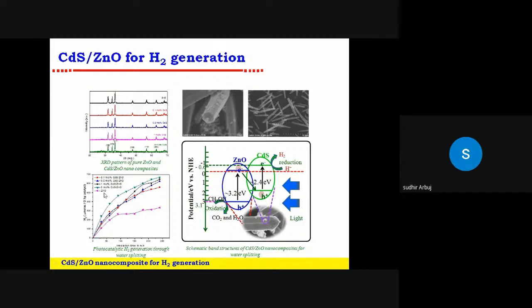So we observed that the 5 mole % CdS-loaded zinc oxide gives the highest hydrogen generation over zinc oxide. Pure zinc oxide does not show good photocatalytic activity for hydrogen generation, but for dye degradation there is good activity. To enhance this activity, we loaded CdS. CdS improves its catalytic activity. It goes from 300 micromoles per 0.1 gram to almost 650 micromoles per gram of hydrogen that we are getting.